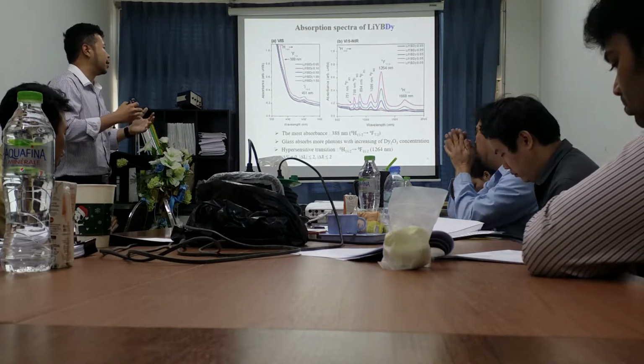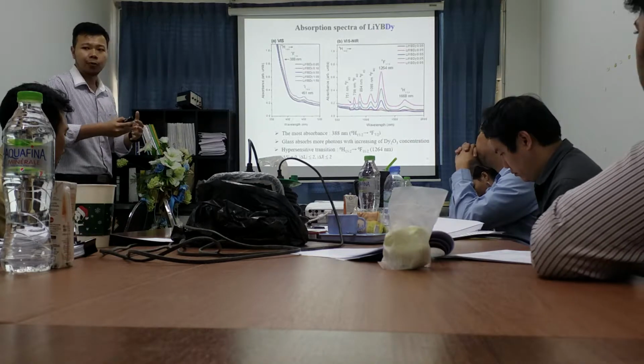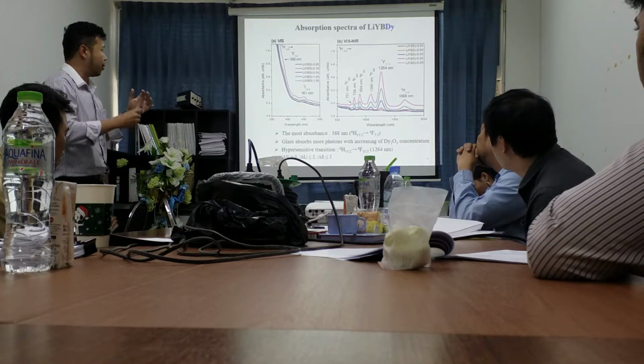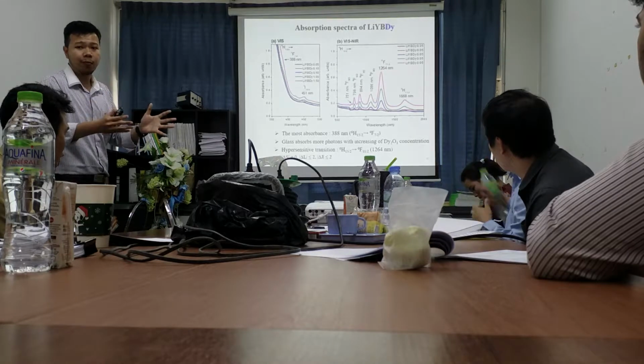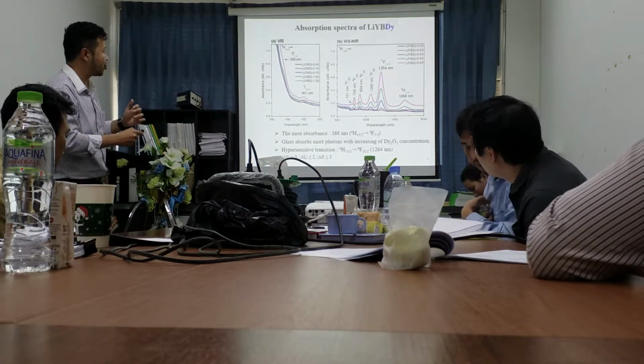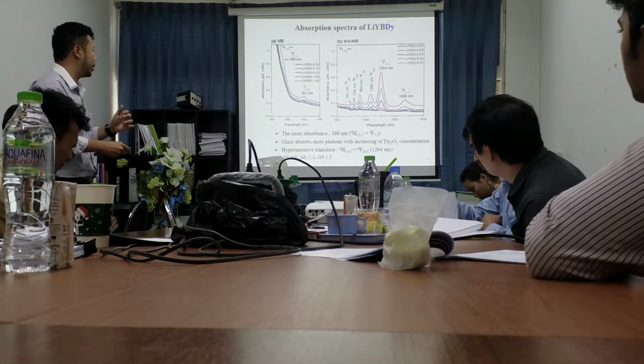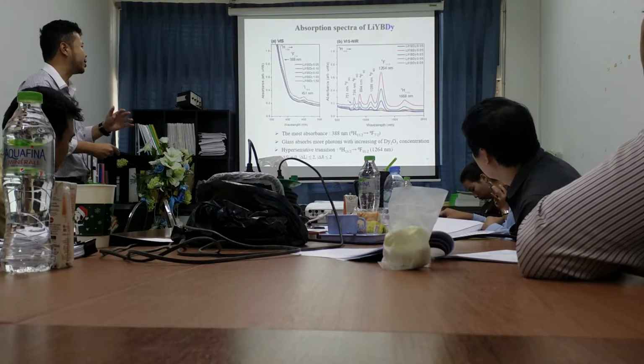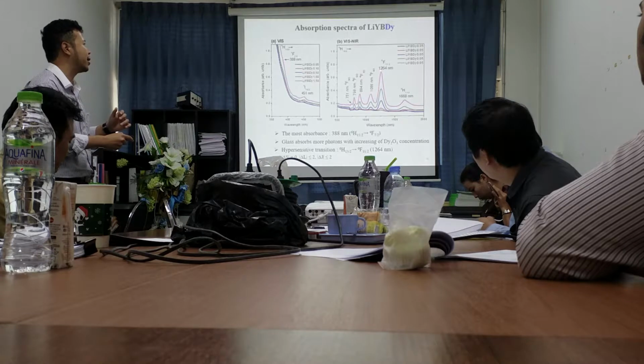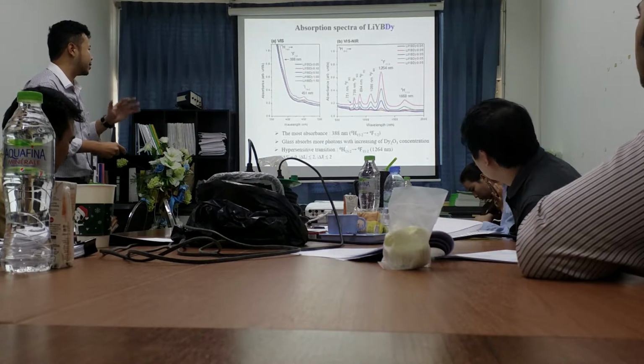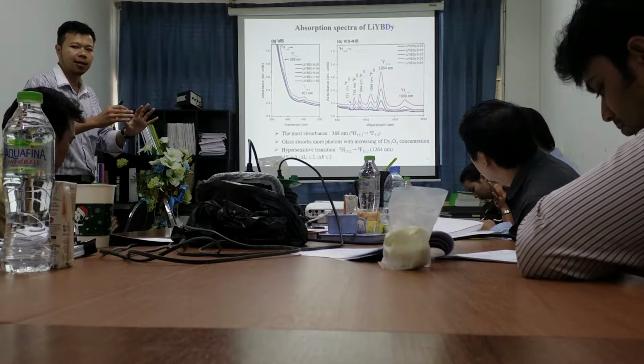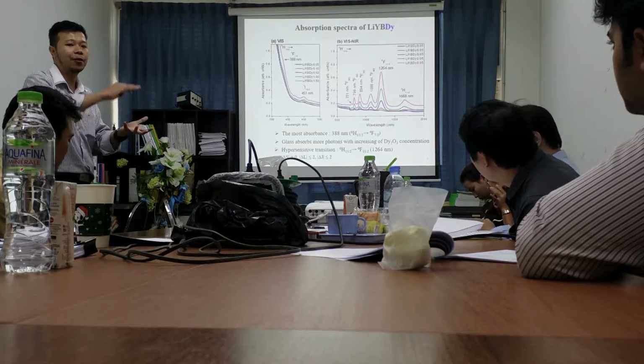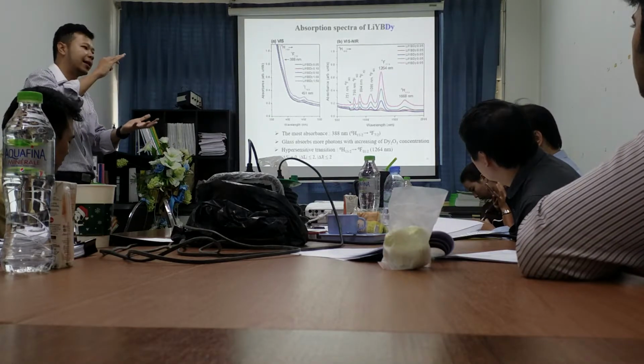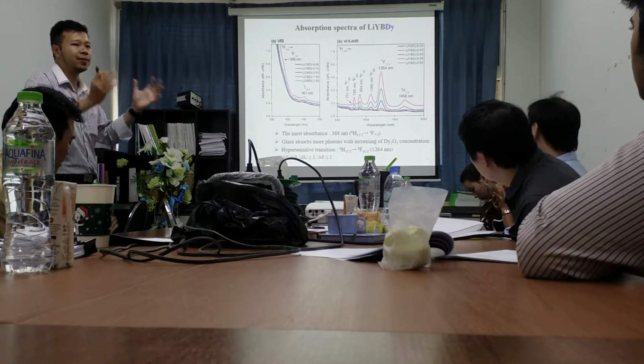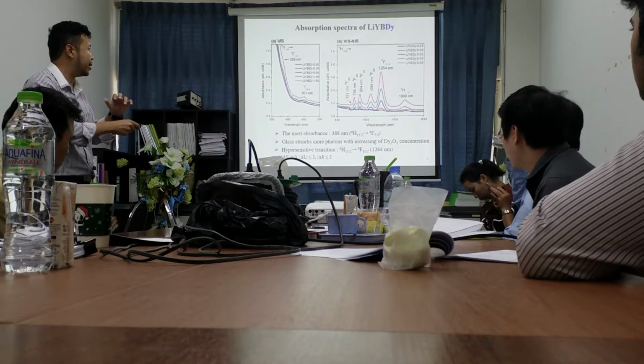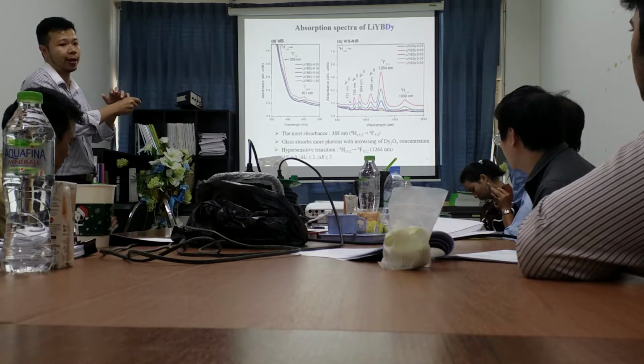Moreover, the absorbance value is more and more. That means this glass can absorb more photons with increment of dysprosium ion in the glass. And we found the hypersensitive transition band at 1284 nanometers. This is the hypersensitive transition that senses the asymmetric environment surrounding the lanthanide ions. If the lanthanide ions are surrounded by an asymmetric host matrix, this grows higher and higher.